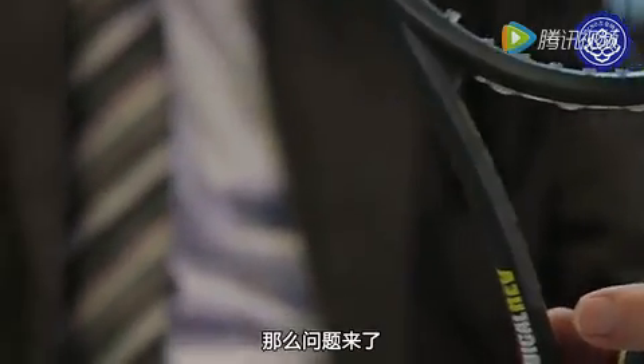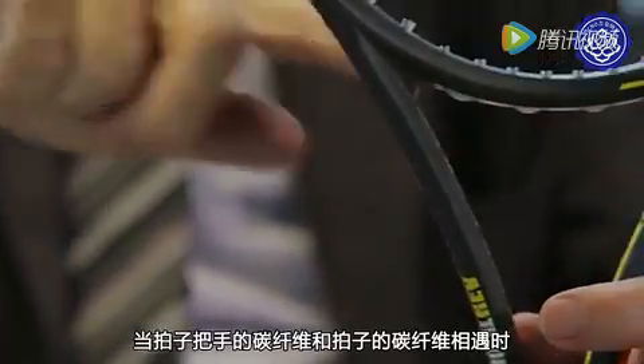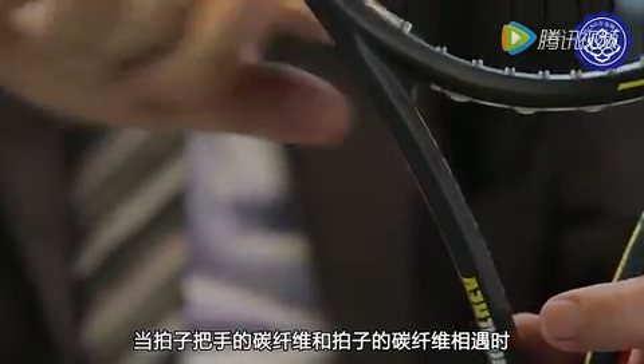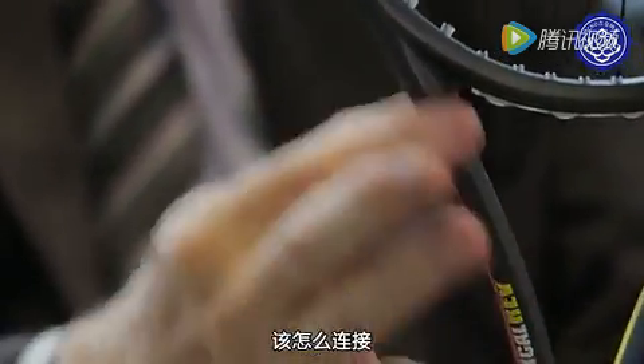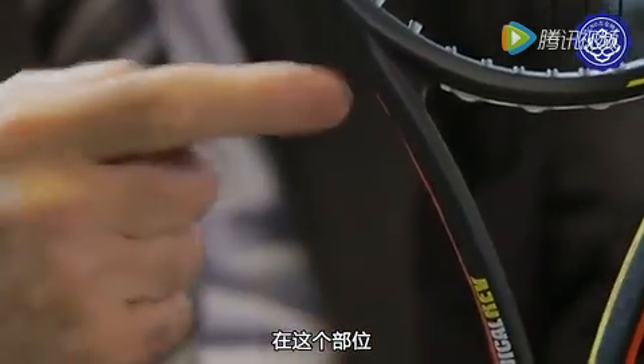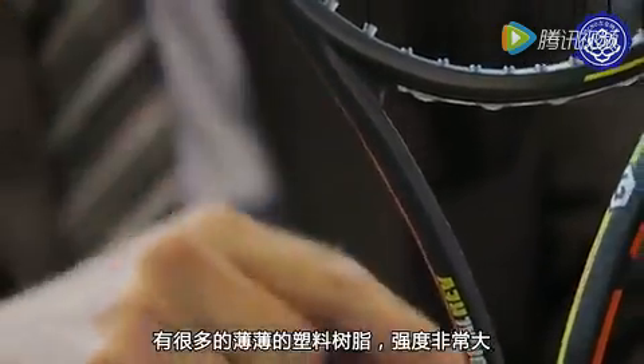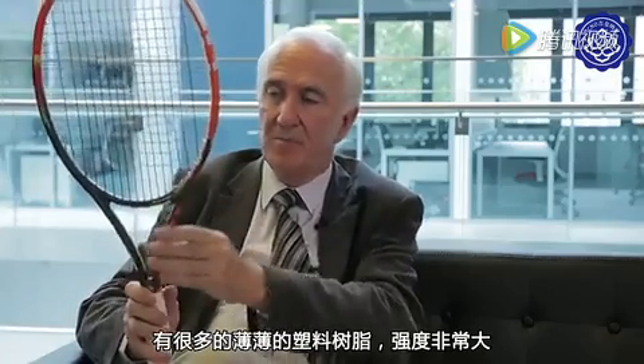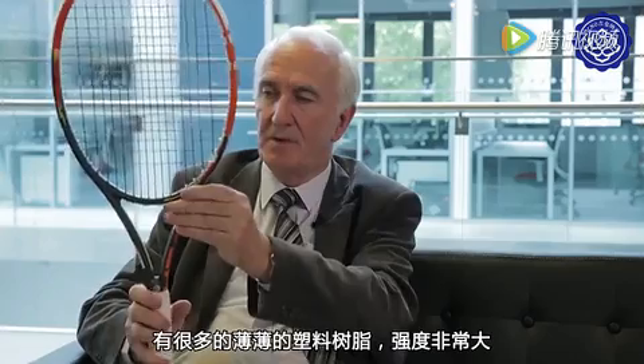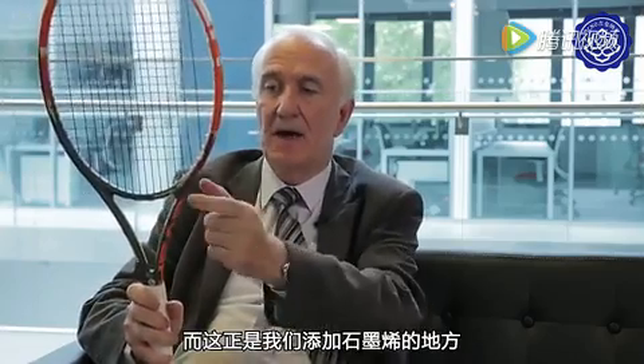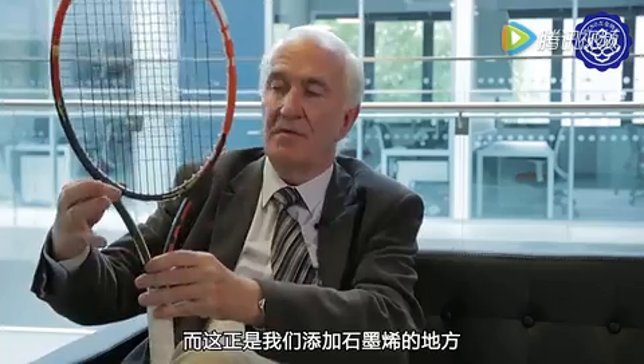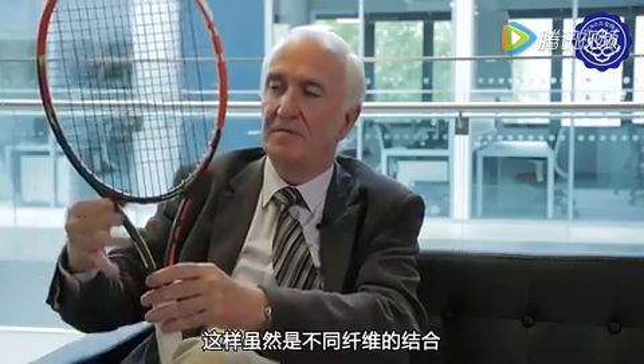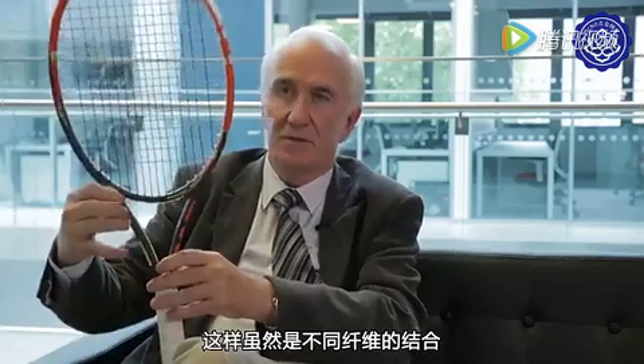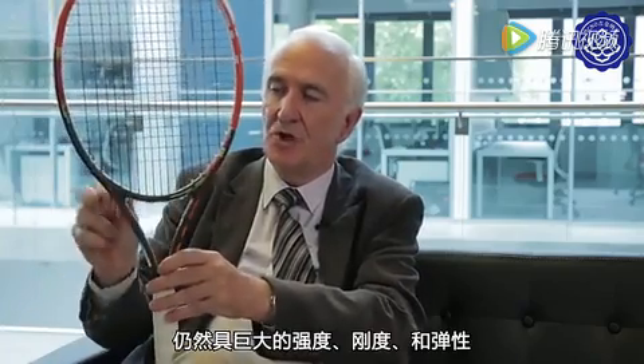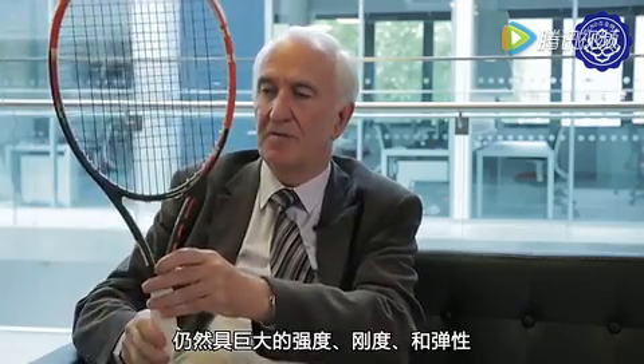But the problem comes where you have the fibers in the shaft meeting the fibers in the head. In that area you have a lot of plastic resin, which is relatively weak compared with the material reinforced by fibers, and this is where you find the graphene is added to give strength, stiffness and resilience in the junction here between the different fibers.